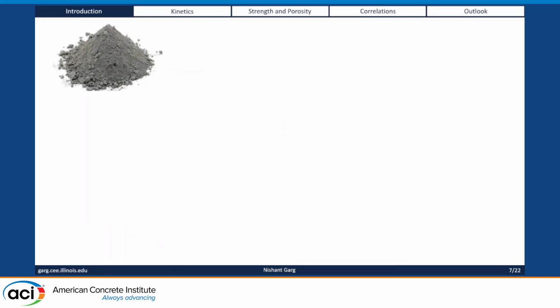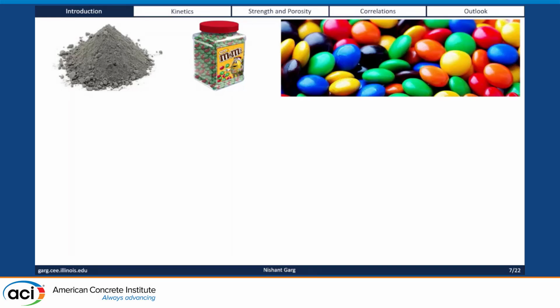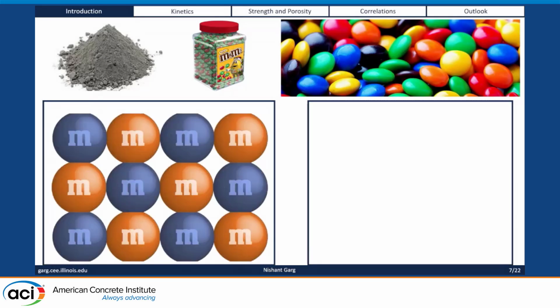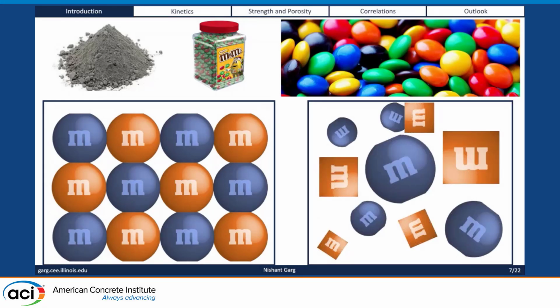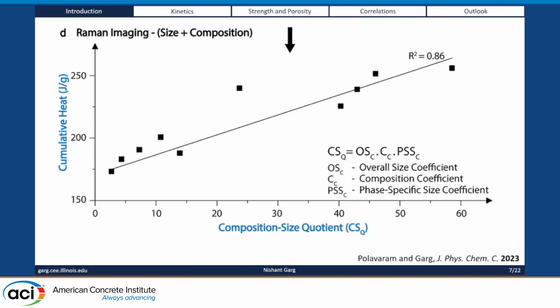How can we better understand this? I was trying to explain this to my kids, and I thought M&Ms would be a good way to explain it. If you think about the cement as a box of M&Ms, you can think of all the cement phases as these different colored M&Ms. And here, you can think of them all being equal size and equally distributed, but in reality, they're random, with different sizes, different shapes, and different orientations. So what we can then do is build a very empirical equation we call the CSQ, which takes into account not only the bulk composition, but the individual particle size distributions of these curves, and we can get a reasonably decent agreement with the 3-day cumulative heat for a series of 10 cements.